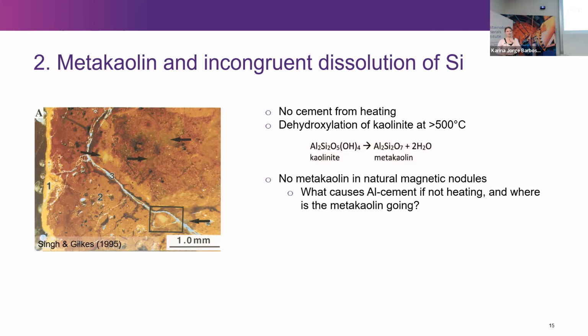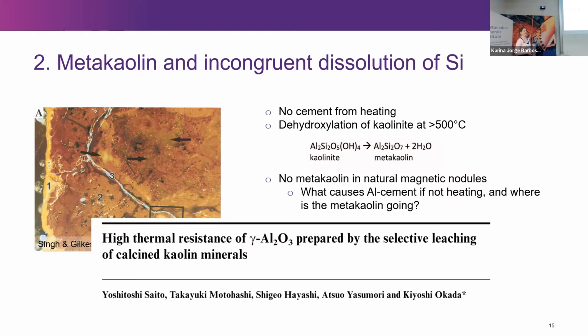So metakaolin, if you're a geologist, might not sound that interesting. I had never really heard of it before. Unless you work in coal seam fires or fly ash, you've probably never heard of it before. If you are a materials scientist, it probably sounds pretty interesting. And like many great discoveries, this came about because I was up at 2 a.m. reading about material science and geopolymers instead of sleeping. But as it turns out, you can make a transition alumina cement by leaching of calcined kaolinite, which is metakaolin. So then the alarm bells start going off.